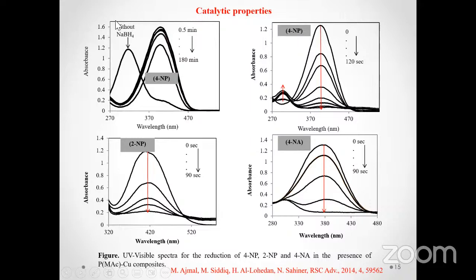And as it can be seen from this first figure, in the absence of a catalyst, when only sodium borohydride was used, even after 180 minutes there was a very small decrease in the concentration, or in the absorbance, of the reaction mixture, which is of course of the 4-nitrophenol, considered a toxic water pollutant. However, when a small amount of a catalyst was used in the same reaction mixture, the same amount of the 4-nitrophenol was degraded within just 120 seconds.